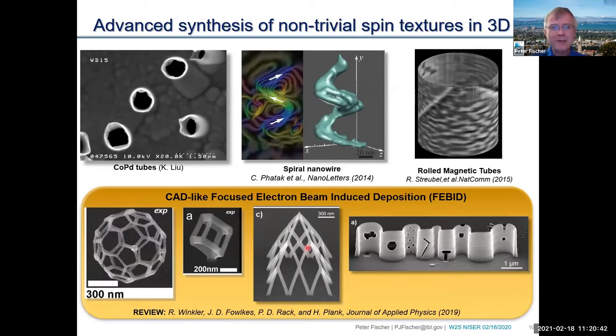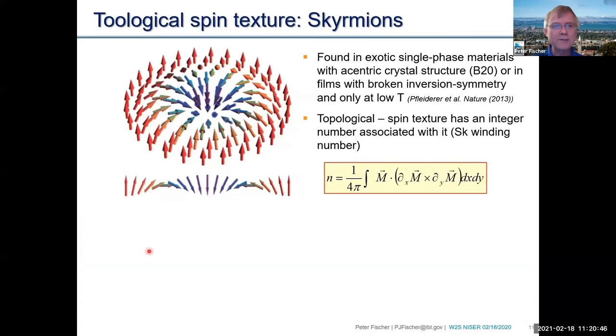Okay, now let me go a little bit back to the flat films again, the 2D systems, and let's talk briefly about one of the spin textures that really is so exciting. These are the skyrmions. Now the skyrmions, as I mentioned, are characterized basically by a full rotation of the magnetization when you go from left to right. Now they were found first by Pfleiderer and really a groundbreaking paper, 2013, in very exotic materials, in a crystal structure, the B20 phase.